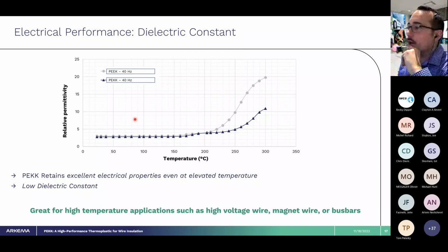It's a little bit better, but really where you see a big difference between our materials is, again, at elevated temperatures. You can't see it that well in this chart, but there's actually a point around 150 to 180 degrees C where we actually have a lower dielectric constant. We do almost intersect here at about 190, but then once you get above 200 degrees C, again, we retain that lower dielectric constant for extended temperatures. So in hot and aggressive environments, PEKK really is a great material.